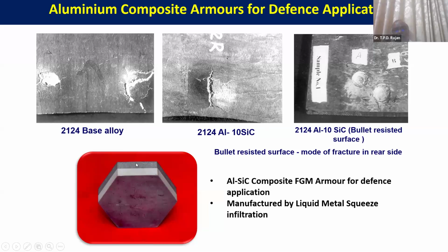So if you have one end with the high silicon content and the other end with liquid pure metal or the pure alloy, then once the bullet hits this high silicon content area, it absorbs by fracture mechanisms, and then by deformation mechanisms, the whole thing is getting arrested. So this is a functionally graded armor material which is developed for defense.